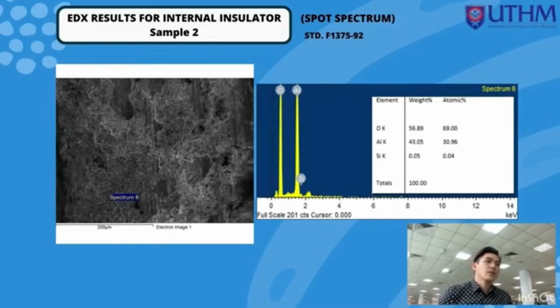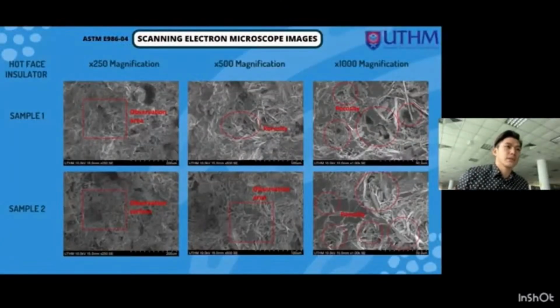And the second sample of the internal insulator, we found the elements, which are aluminum oxide and also silica. So as we can see, oxide always takes the highest weight percentage in the spectrum. This is the last part of the results, which is about the scanning electron microscope image.